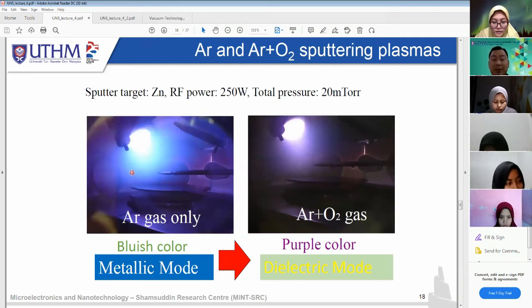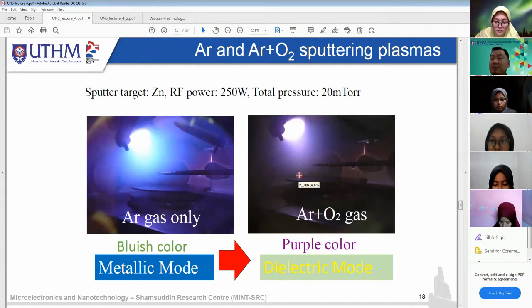Okay, so this is a sputtering plasma that we have in the lab. So this is the example. Just now I showed the inside of the chamber, we have two targets, on the left and on the right. When we put one target on the left, in this case we use zinc as our sputter target, we can create this bluish color metallic mode of plasma. We use argon gas for discharge, and then we add oxygen into the chamber. You can see the color of the plasma change from bluish to purple, so from a metallic mode to a dielectric mode because of the oxygen that we put inside the chamber.